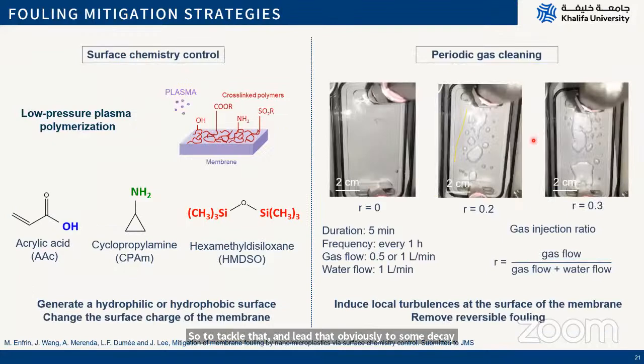So to tackle this, we developed two strategies. First, me being a material person, we tried to modify the surface of the membranes to actually make them more repellent or adsorptive for microplastics. So we tried to control the molecular interactions between the two. But we also tried to understand how we can affect the flow of microplastics in the vicinity of the membrane surface to potentially prevent their adhesion. So we look both at surface chemistry control and gas cleaning or air scouring in that case.